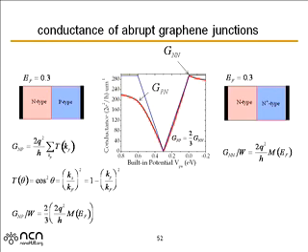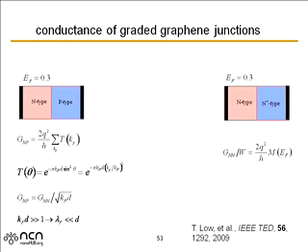Okay. But as I mentioned earlier, that's not nearly enough. That explains only a small part; the experimentally observed asymmetry is 10 times more. So it's much more pronounced than this. And the experimentally observed asymmetry is due to the fact that there is some transition region here that you have to tunnel through. So if we use as our transmission coefficient the expression we got from this WKB treatment, and if we do the integration over all of the KYs that come in, we'll find that the conductance is reduced by this factor, the square root of the Fermi wave vector times the depletion region thickness. So the thicker it becomes, the smaller this conductance becomes.